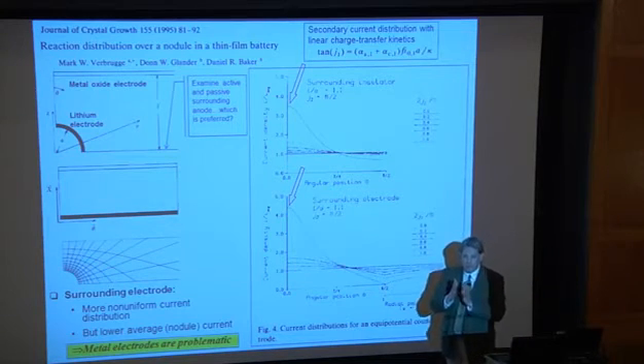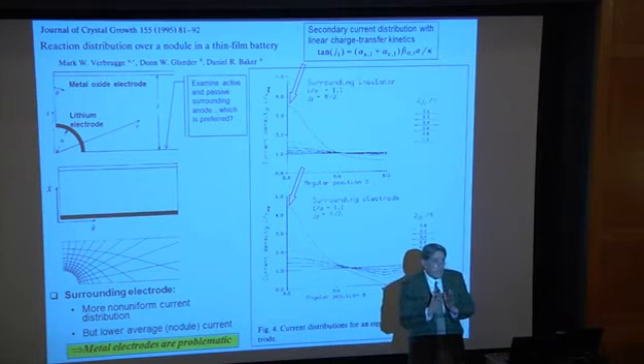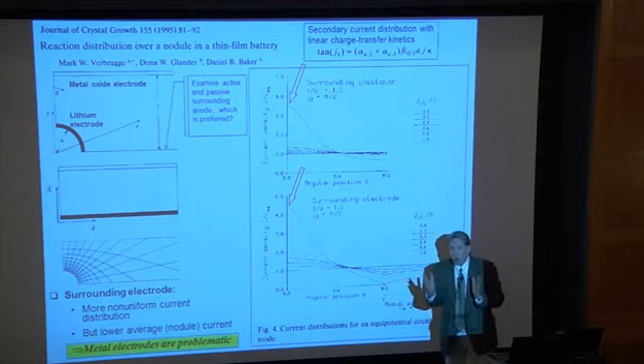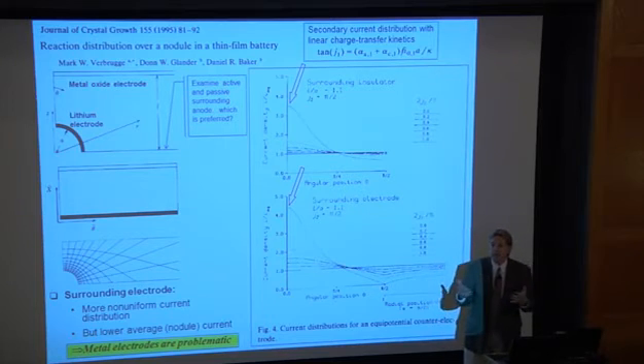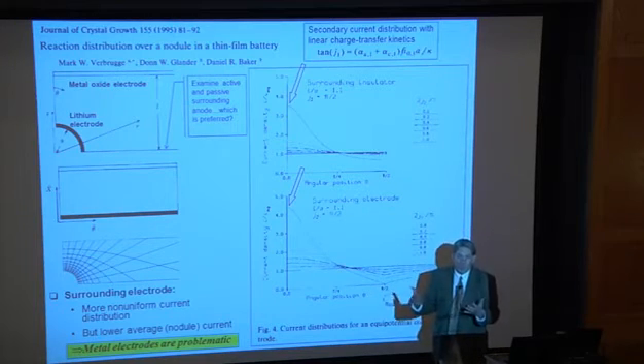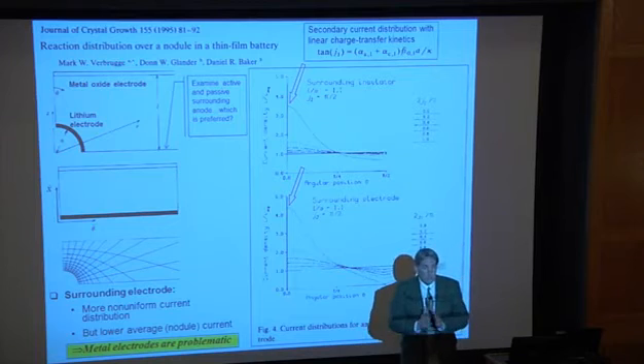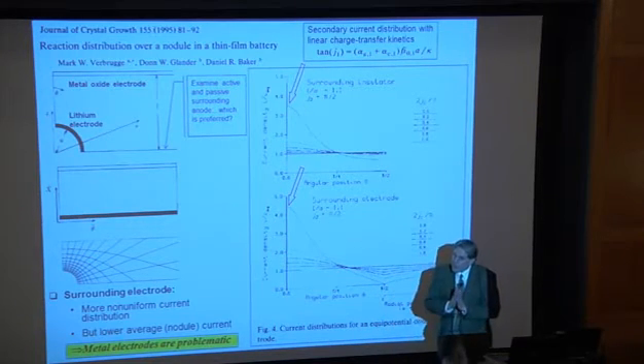We have this 25-micron thick separator. The non-aqueous electrolytes are almost 2 orders of magnitude less conductive than, say, a sulfuric acid electrolyte used in lead-acid batteries to start a car at very cold temperatures, minus 30 degrees C. So at any rate, we go to a thin film geometry.